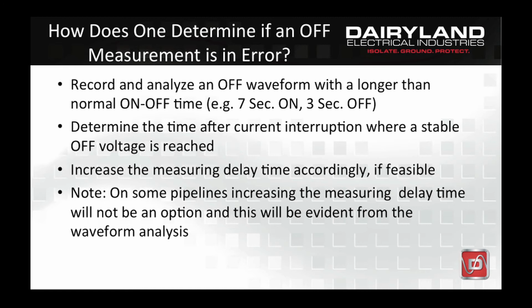So how does one determine if an instant off CP measurement on a decoupled pipeline is likely to be in error? To answer this question, it is recommended that one plot, record and analyze an off waveform with a longer than normal on-off cycle, such as 7 seconds on and 3 seconds off, for example, and sometimes even longer.